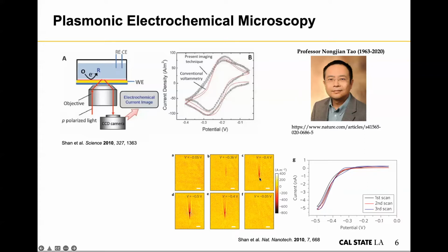And you can see here, those individual tails are characteristic signals that you can see from SPR images, originating from scattering of the plasmonic wave by a nanoparticle. You can think of it as a boat moving in the river. You will see those waves behind the boat. Now the difference is that the particle is not moving, but it's the plasmonic wave that is moving. But anyway, we usually see a long tail behind a nanoparticle, and we actually use this tail to extract signals for probing nanoparticles because, as I mentioned earlier, optical imaging techniques are subject to diffraction limits. So you have a spatial resolution of about 200 nanometers, but we can actually use the technique to look at particles that are much smaller. For example, I think in this paper, they claim that an 8 nanometer platinum nanoparticle can be probed.